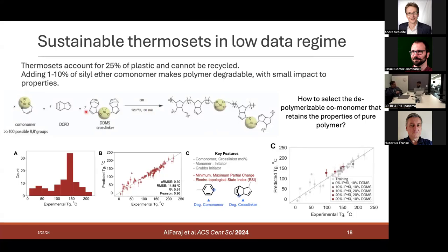So again, these folks designed this silyl ether additive, and it's a very similar theme, right? Where there is a clear design space of what are all the silyl ethers I could possibly construct, right? I have an R prime, some double bond here to be included in the chain, such that the polymer that I make retains the properties of the pristine, non-cleavable, commercially used polymer. And in this particular example, again, we were in couple-100-point territory, which is not trivial, but it's not big data either.